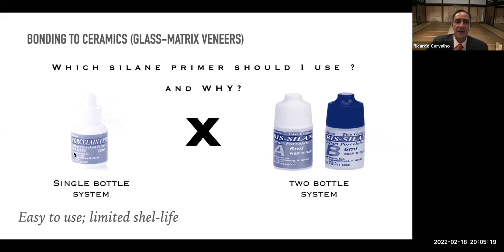Usually, a single bottle silane will last maybe up to 2 years, but they are highly sensitive to heat. So if you have warm weather, if you don't have a proper fridge, etc., to store a silane solution in the heat of, let's say, 25 to 30 degrees for a longer period, it may just compromise the whole solution. And this is something that does not happen with the two bottle system, because what is a two bottle system? Well, one side is the silane and the other side is the acid. Once you mix, you activate the reaction, and then you have to allow some time for the reaction to occur, and you can utilize it for silanization. The advantage here is the stability. Since the acid is not mixed with the silane before, you have a prolonged shelf life.